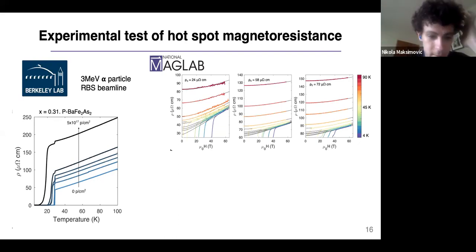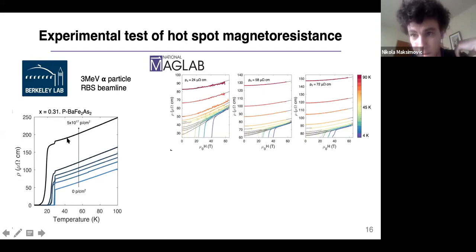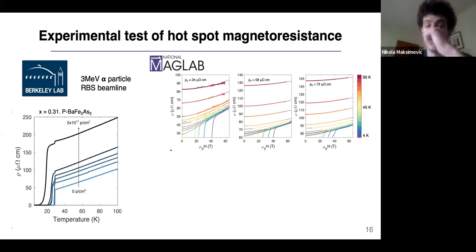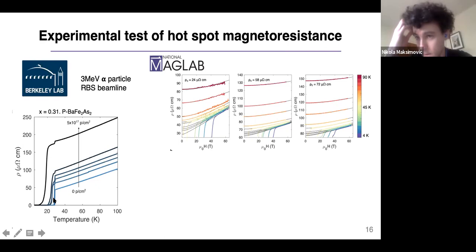This is similar to the question that Chimiao was asking, about the fact that we don't seem to see very significant changes in the temperature dependent resistivity as we disorder the samples. Like you mentioned, Achim Rosch's paper, you should see qualitative changes in the power law with disorder, but it may be that we're just at too high a temperature. We have to go through Rosch's paper in detail and see what the different temperature scales are in these different scaling regimes. So it's not something that I have a good answer to. Okay, well, thank you.